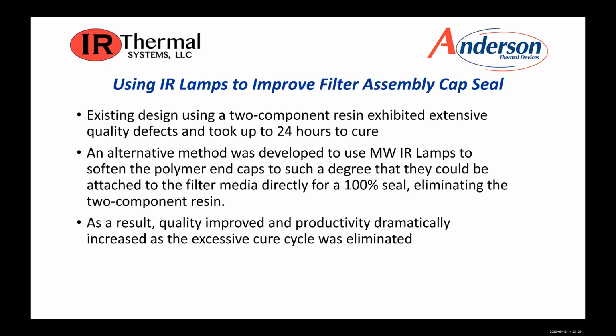With the utilization of the infrared, we were able to take a filter. The polymer end caps were reformulated slightly so that the polymer would allow a softening when it was heated. So we basically engaged the infrared onto both sides of the assembly. We heat it to the point that it becomes softened properly. The infrared device then retracts below, and automatically the end cap was pressed onto the filter pleated filter assembly, creating that end cap.